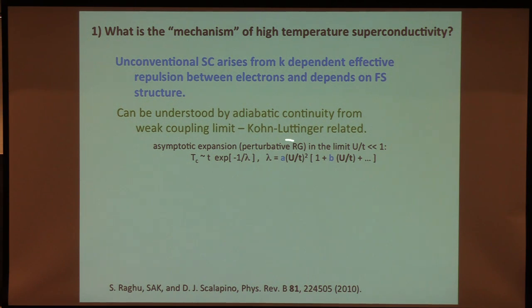The physics that leads to this is actually quite different from what they focused on. It has actually nothing whatsoever to do with Friedel oscillations and singularities to do with the Fermi surface. In fact, you can prove that for a circular Fermi surface in 2 dimensions, this coefficient A vanishes. So the details of this depend on band structure in some complicated way.